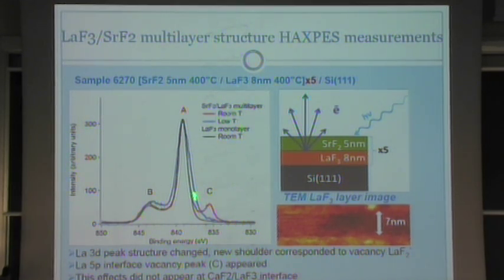Here the green curve presents a monolayer structure, and the red one is the first spectrum from the multilayer structure. So we've got special interface changes which promote the creation of fluorine vacancies in the interface. As you can see below on the slide, it's a transmission electron microscopy image, and you can see that this is the lanthanum fluoride layer, and its borders are sharp, and we've got good epitaxial quality of our layers.